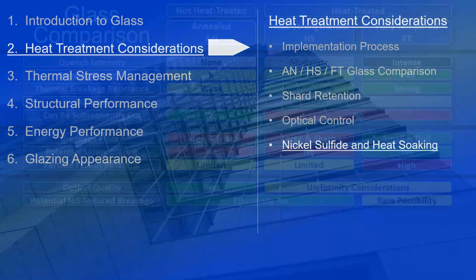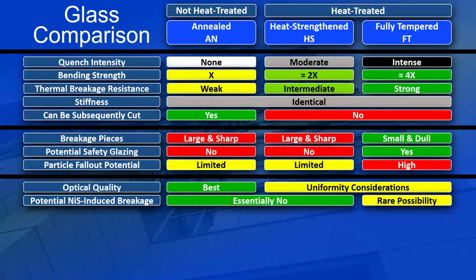Heat treatment considerations, nickel sulfide and heat soaking. Many of us have heard of spontaneous breakage, and those new to the glass industry might not be aware that glass can spontaneously break. With nickel sulfide, one of the other things that is a cause for concern is that if there is a nickel sulfide breakage on an inboard uncoated light from an unknown float manufacturer, that breakage may be associated incorrectly with the outboard coated low E light. And so that's one of the reasons that we want to be careful about how we talk about nickel sulfide breakage. With heat strengthened and annealed glass, the risk of nickel sulfide breakage is very, very low, essentially none. With fully tempered glass, there is a possibility for breakage.